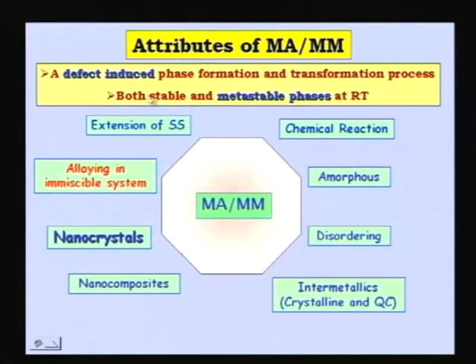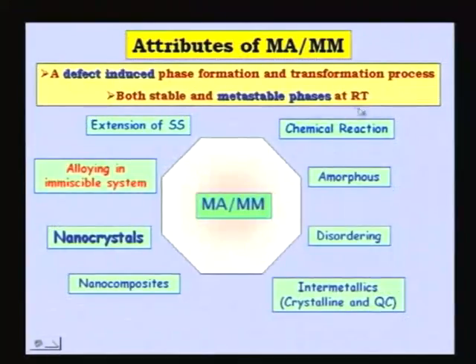And because of this, you can have either stable phases or metastable phases forming at room temperature. This is very crucial. All these phases are not really happening at high temperature, they are all happening at room temperature or close to room temperature. We will talk about the temperature during ball milling at some point of time. Okay, so you can take it for granted that more or less the temperature is close to room temperature. So all these processes occur near room temperature.